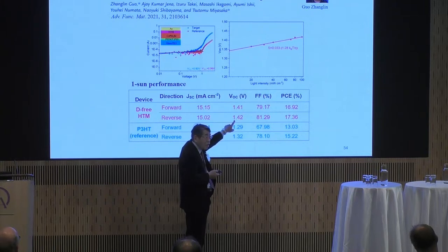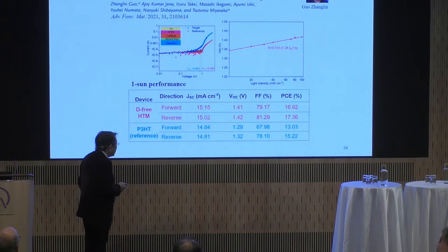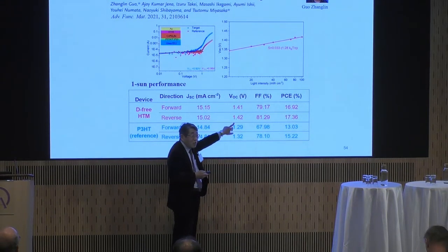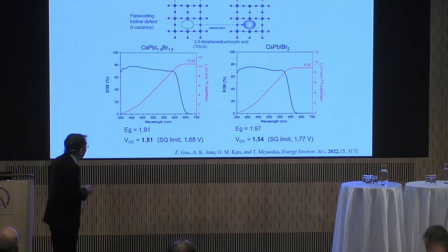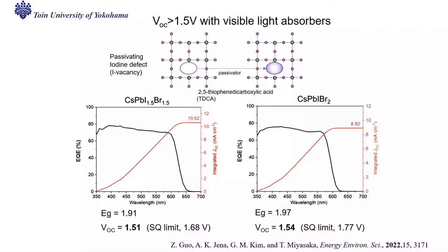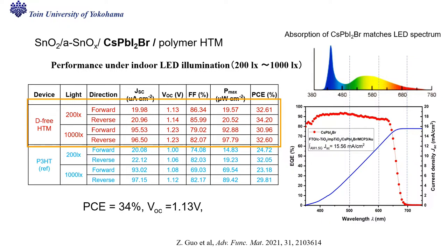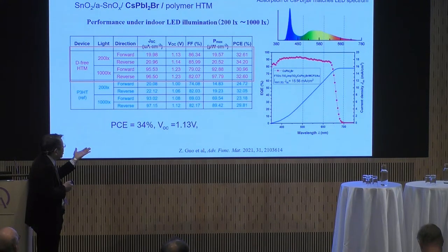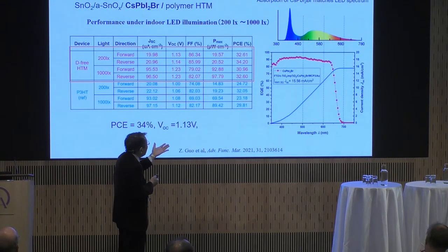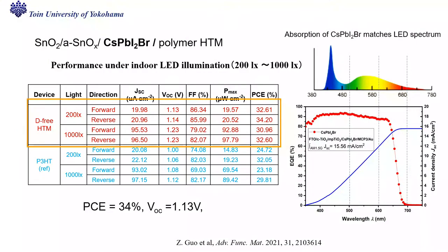This was relatively high photovoltage from the single solar cell. For example, silicon solar cell, this voltage is 0.7 to 0.8. And we could further enhance photovoltage, exceeding 1.5, by passivating the iodine defect by using this kind of organic materials. Interesting news is if we expose the device to indoor LED light, power conversion efficiency reached over 30%, because there is a very good matching between the light emission spectrum and absorption spectral sensitivity. So there was no loss in harvesting light indoors, because it's a visible light sensitive photovoltaic cell.